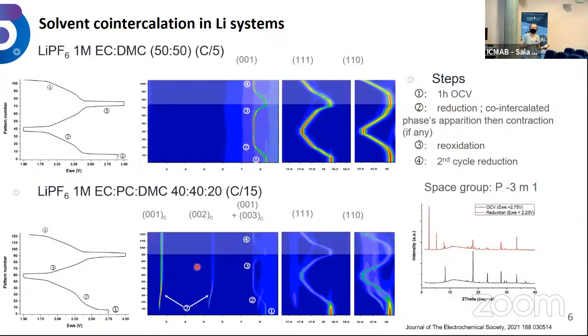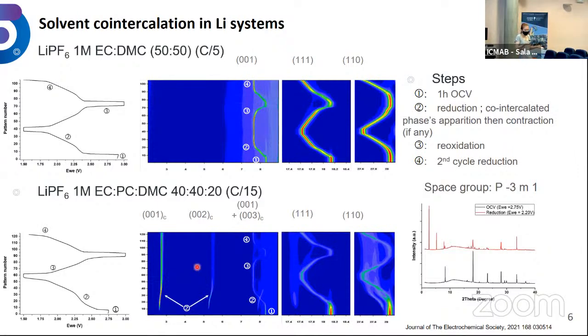We also tried to make a second reduction, but nothing was much different. You can continue to cycle on your material even if you have co-intercalation, but it's not reversible. It will always be here even if you try to cycle 5-6 cycles.